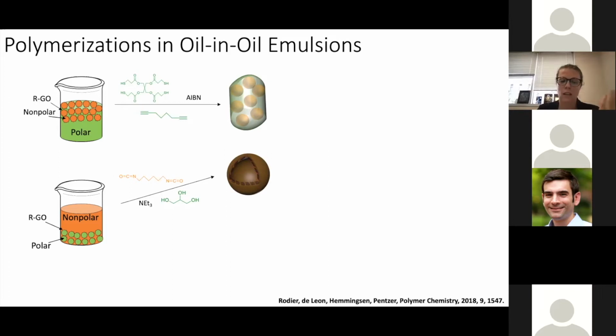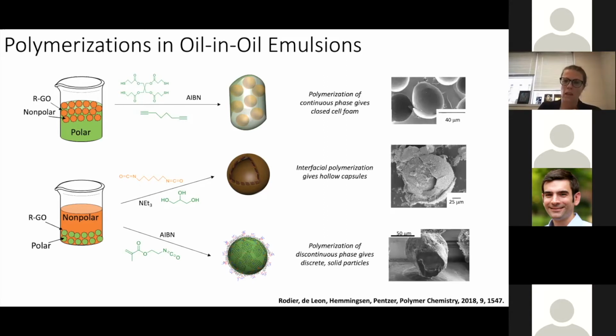And then lastly, if we have a droplet that is composed of this isocyanate functionalized methacrylate, and again, some AIBN, we could heat this up, and provided the emulsion is stable, we could do this free radical dispersion polymerization and get a polymer armored with the RGO nanosheets. And so Brad showed that he could indeed access a closed cell foam, a hollow capsule.